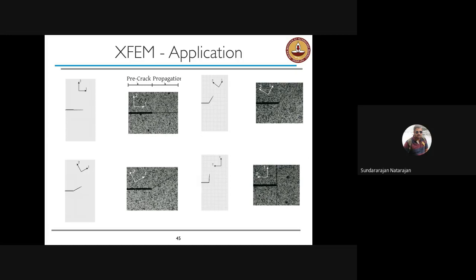The one exception to this is when the crack is oriented perpendicular to the fiber. Experiments show that there is a branch, and that happens at the crack tip, which the XFEM was not able to capture. That is because crack branching has to be an input to the model so that it knows when the crack has to branch. Of course, when we did the simulation back in 2011, we didn't have that necessary information. So that's the reason why it was predicting that the crack grows along one direction and not in two directions, as we see in experiments.